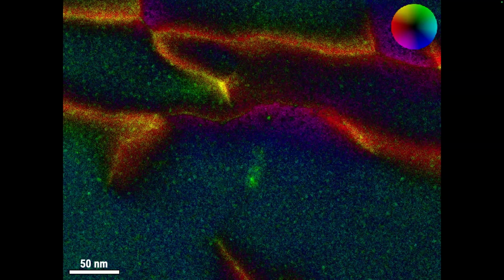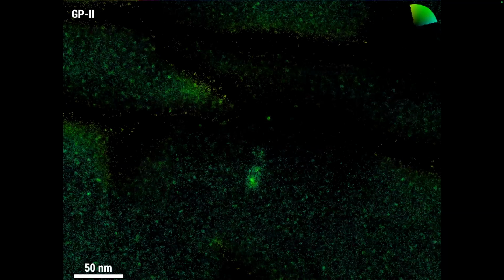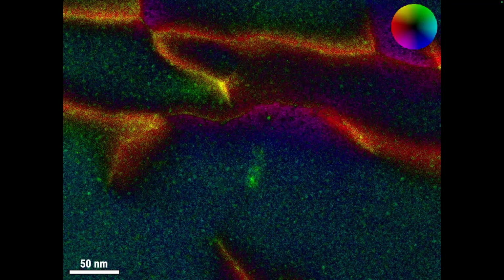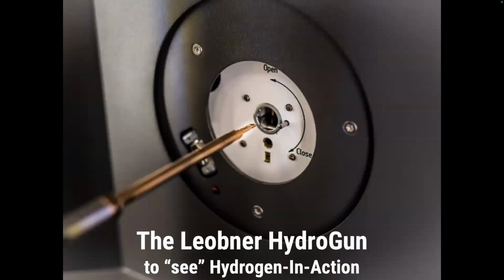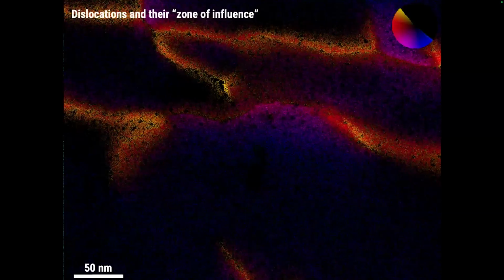And what we can do with this is image segmentation. This is the aluminum alloy matrix. The contrast is not very good, but we can separate the GP zones and the dislocations. Maybe I can go back. You see, this is the electric field image. Then I have the aluminum alloy matrix. So imagine that if we charge hydrogen here, we monitor what happens with the signal of the electric field in the sample. This is one of the ideas we have. This is the dislocation, and you can see that the dislocation also has a halo here, which I call the zone of dislocation influence. It is not directly the strain field.